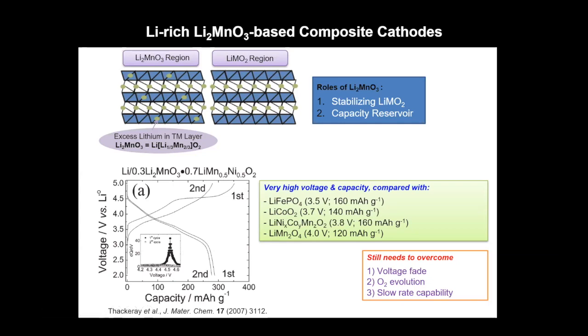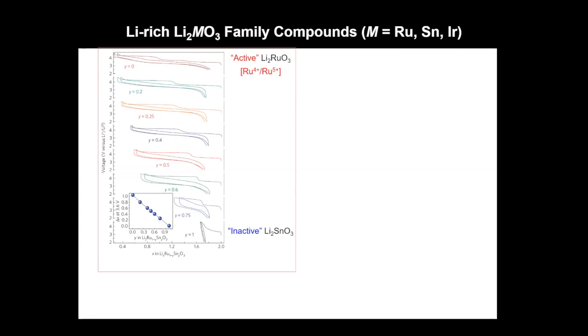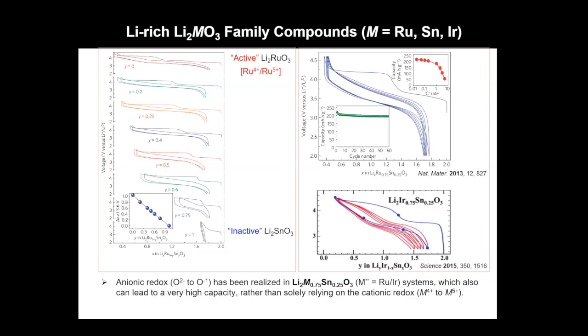So in this same family, there have been other materials discovered other than lithium manganese oxide. These other materials exhibit interesting properties as well, with other metals such as ruthenium, tin, iridium, and so forth. One of the interesting things about these materials is that there's also evidence of anionic redox that can occur during charge and discharge, rather than solely relying on the cation to produce all of the redox capacity. So that's a very interesting and very active area that lots of people are exploring.